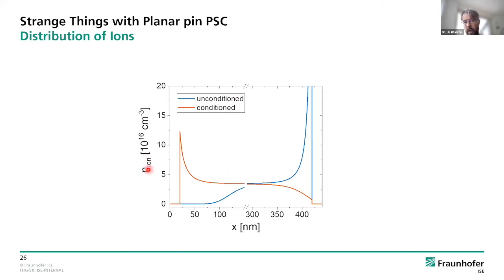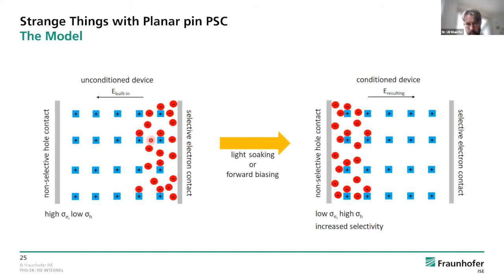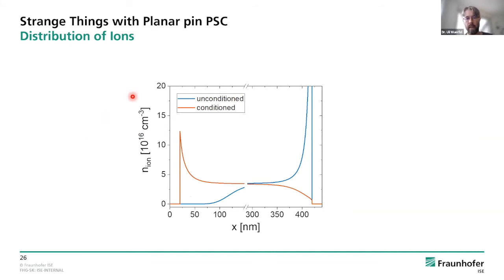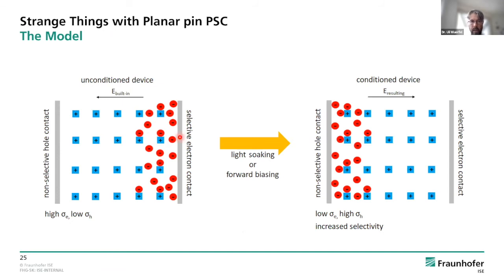First of all, we started with a homogeneous distribution of both kinds of ionic species. It was not looking like this in the beginning, but we told the computer that evenly distributed positive and negative charges. The positive keep their place, they're fixed, and the negative can move. Here you can see that in the unconditioned device, the ionic density of the mobile species is peaking in front of the electron contact, and there is nearly nothing going on near the hole contact. But after the light soaking under open circuit condition, this conditioned device has the ionic species just the other way around. They peak close to the hole contact, and we have very few at the electron contact interface. So there you can see exactly in numbers what I tried to explain with the schemes.